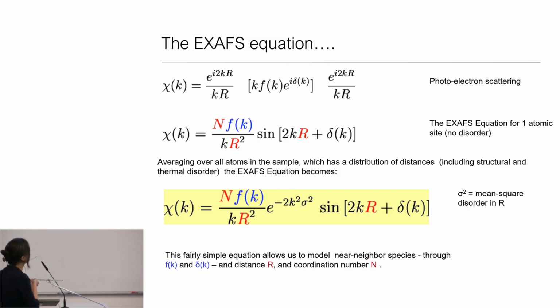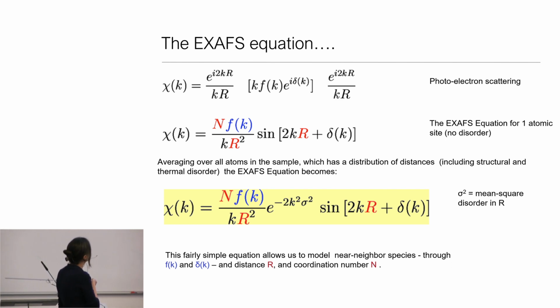This is just the XAFS equation for one atomic site, but you can see that it's dependent on n, the coordination number. It's dependent on r, the distance of the photoabsorber to its nearest neighbor, and it's also dependent on the phase. I'm going to break this down visually, how each of these things impacts it. But the other important component we have in XAFS is the disorder term, or what we often refer to as the Debye-Waller. That's represented as sigma squared, and it's a mean square disorder in R. So this is sort of the analogy of B factors in crystallography.